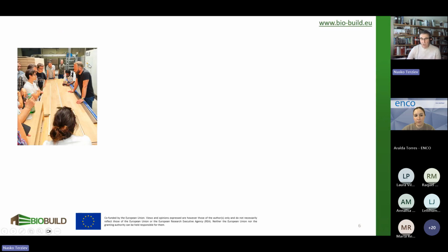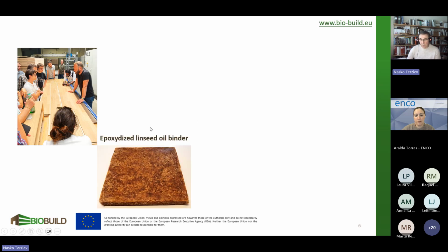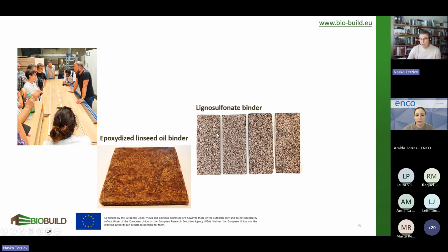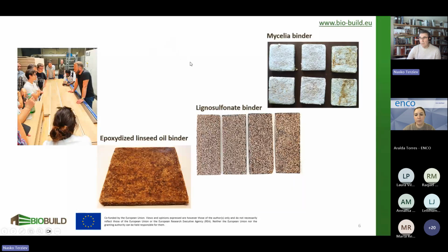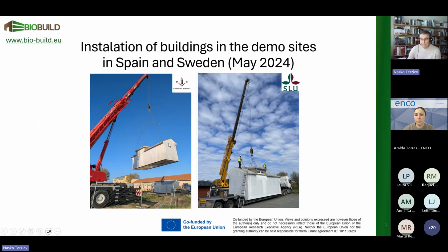So these 4 products, the flooring and 3 types of panels, should be tested in real conditions. Since we're in the middle of the project, we have already developed the technology for flooring. The flooring is in a stage of preparation and testing. Then we have composites with epoxidized linseed oil as binder. This is a lignosulfonate binder based on lignin derivatives from the pulp and paper industry. And finally, we have mycelium binder. We have to test it in, let's say, real building structures.